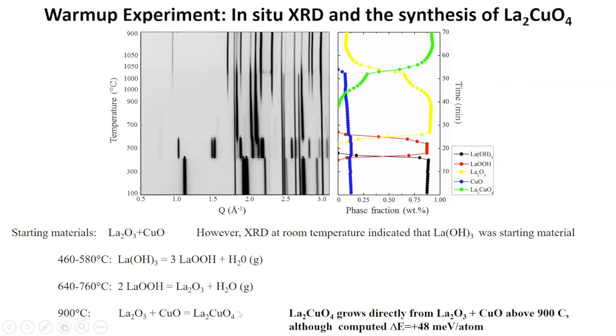And so what we found from the total energy calculations would be that this reaction is thermodynamically not favored, meaning that you'd have to provide 48 meV per atom to go from the reactants to the product, 48 meV per atom. So of course, I have to point out to you that lanthanum cuprate does exist. It forms by this reaction. And so the interpretation that we would have would be that possibly thermodynamics is not the only thing at play here. Kinetics could also stabilize this reaction.